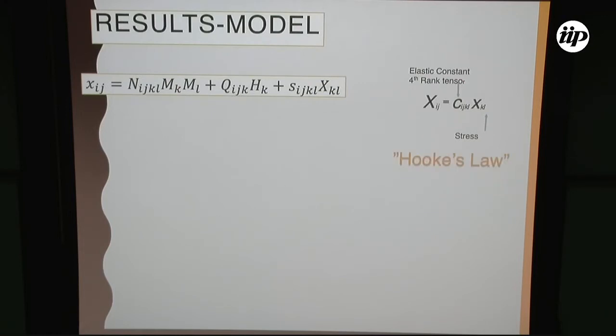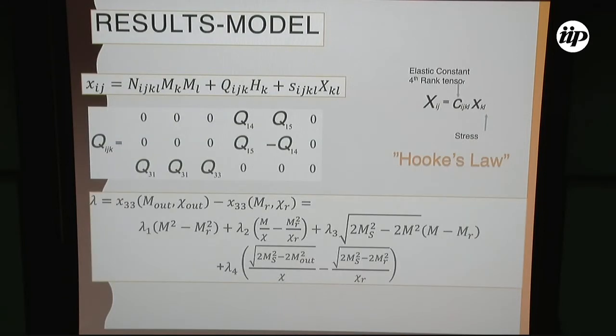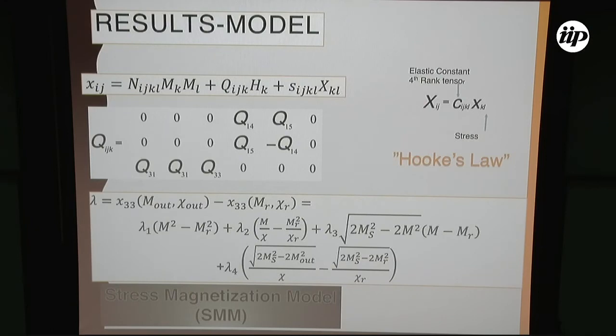When the magnetic field is applied to the sample, there is a change in the size of the ferrite grain, and so there is a force associated with the environment, the ferromagnetic environment. And they include a new term associated with the stress. They use the same matrix and obtain a more complex expression. The magnetostriction coefficient appears in the third and fourth terms, associated with the square of the magnetization, and the other terms are associated with the remanent magnetization and saturation magnetization. This is a stress magnetization model.